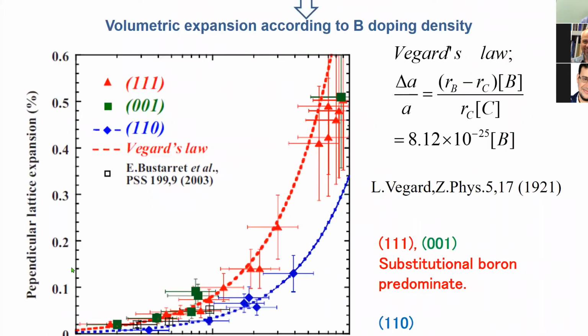So here's another explanation of the boron doping effect. Boron is an atom larger than carbon when we make the lattice. The atomic distance - just from calculations, very old properties - we use Vegard's law, which is, I don't know, from the last century, a theory or just a law. Anyway, when we increase the boron concentration, we observe perpendicular lattice expansion by X-ray measurement.